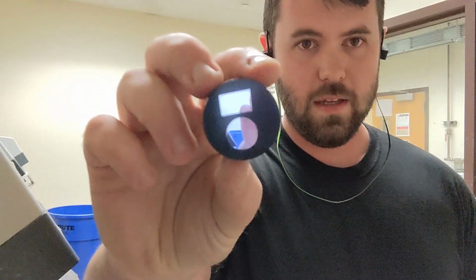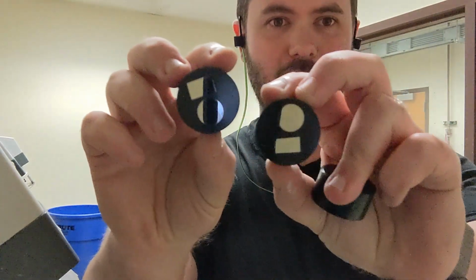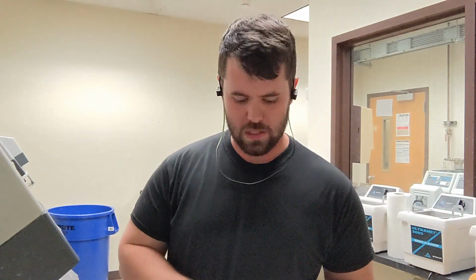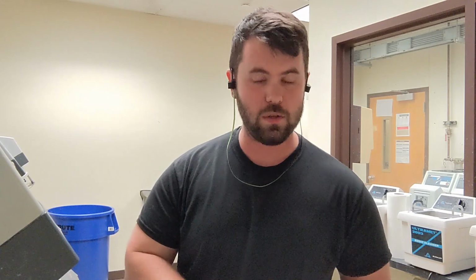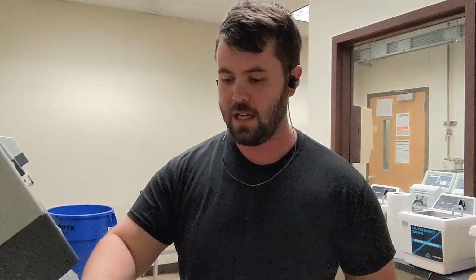The final step is done. Our 0.3 micron polishing is finished, and here is our sample. As you can see, very shiny, very smooth, mirror finish, just like we wanted. So before we go on to etching, which is the final step before the microscope, I need to stress one thing, which you probably heard about in high school and at UT here and in other labs, and that is the importance of cleaning up after yourself.